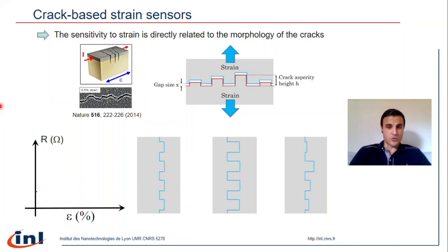The key point to control the sensitivity is to control the morphology of the cracks, which have a certain roughness, as you can see here on this top view SEM image. First, consider an ideal crack, far from reality, a crack which has no dispersion on the size of the asperities within the crack. In this case, the sensitivity curve would look like this. The resistance remains quite stable until the contact is lost between the asperities within the crack.